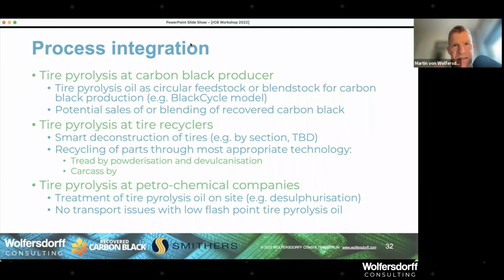But clearly, it is not as good as a renewable feedstock, which will go in with a negative carbon balance because in its lifetime, it has actually captured carbon. And that negative footprint, of course, is not in the scope 1. The scope 1 is likely the same as the furnace process because it's manufactured in the furnace process. But the negative carbon footprint would come in scope 3. So I hope that is answered.